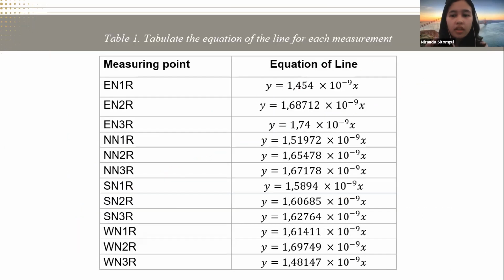Okay, from the result of the data plot, a regression is performed to find the gradient to see the response of temperature noise to its frequency. The result of the trend line and line equation obtained in each graph we can see in Table 1, which tabulates the equation of the line for each measurement. We can see there are 12 measurement points, and the gradient is quite small, at parts per billion, which indicates that the temperature noise response to frequency is small or not influenced.